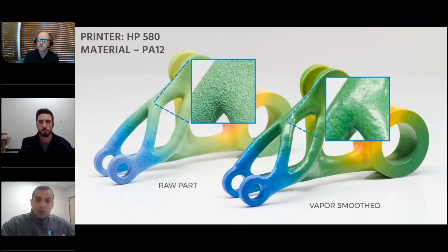For example, elongation at break. Depending on the material, if it's nylon 12, you should expect out of our process an improvement of about 25 to 30%. If it's nylon 11, you're going to see improvements of about 100 to 150%. And you may say, wow, 150%, you're stretching. Think of a dog bone, for example, a tensile bar. Stretching a nylon 11 part that much, you may say, you must be softening the material.